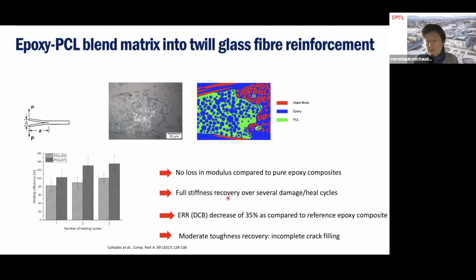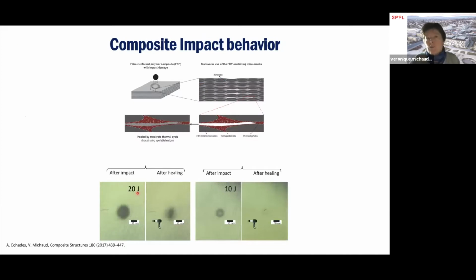We also checked that there was no loss in modulus compared to pure epoxy reference composites, and that we had a stiffness recovery over several damage and heal cycles. The energy release rate, however, decreased quite a lot as compared to the reference epoxy composite due to the loss of toughness of the matrix. And we had a moderate toughness recovery due to incomplete crack fill. So we had something that worked, but of course, normally you don't have a DCB test happening in real life. So damage could be, for example, under the form of an impact, creating some micro cracks. And we looked to see if we could really heal the micro cracks.